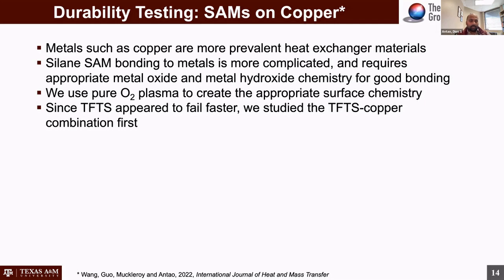And after trying a bunch of different aspects, one of which we've not really tested as yet, we ended up on pure oxygen plasma treatments. If there was any air, so nitrogen or some of the other components of air present in the system, the coatings weren't as good as a pure oxygen plasma. So we had to do multiple purges of the plasma treatment chamber in order to achieve that pure oxygen environment